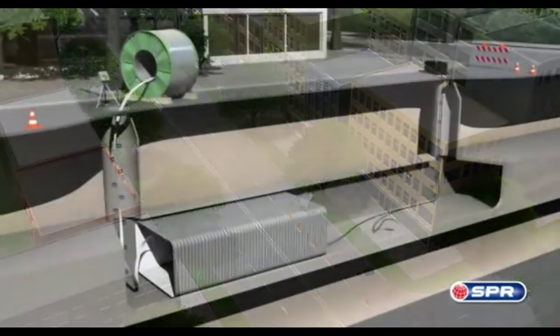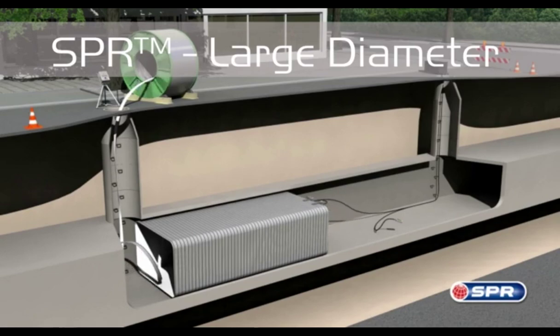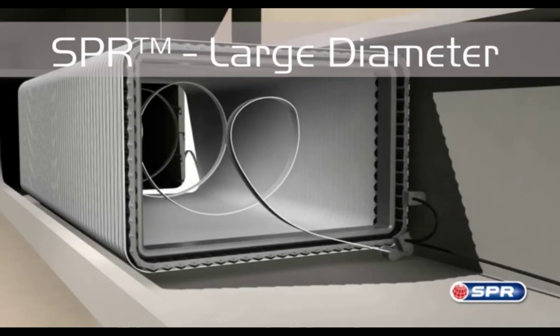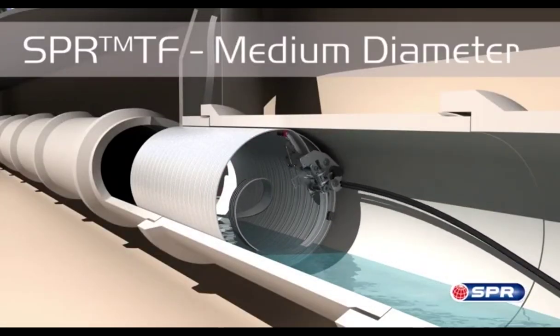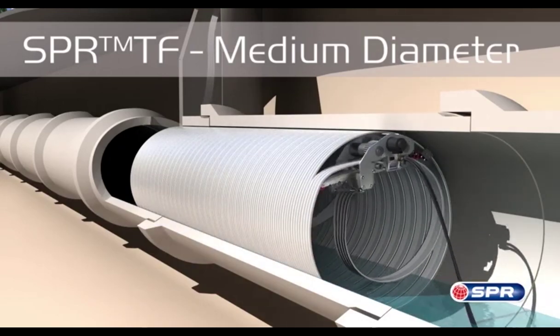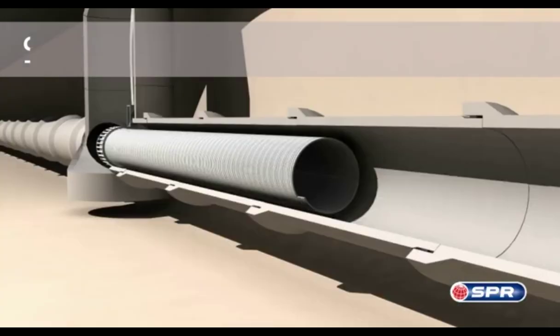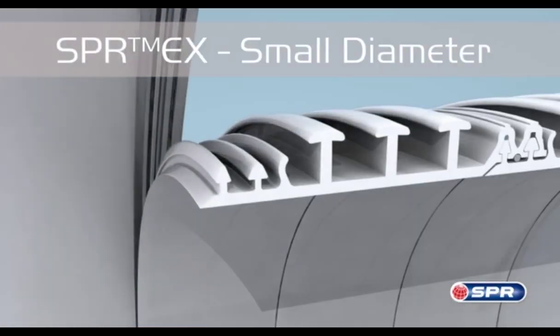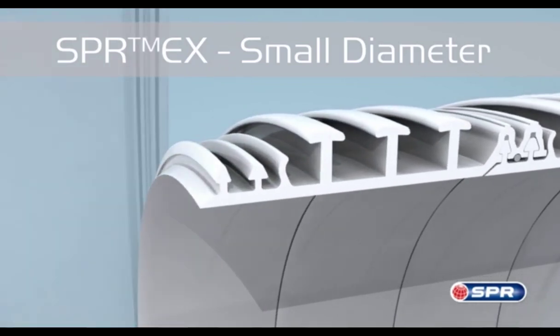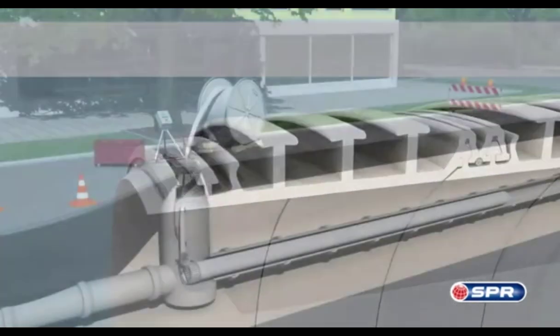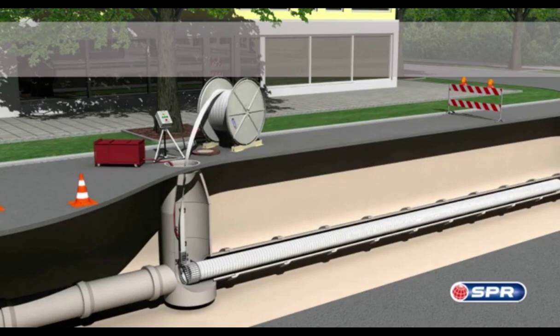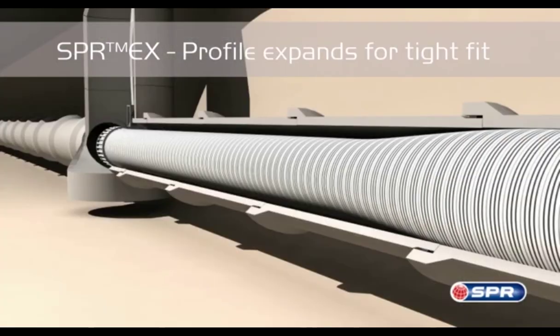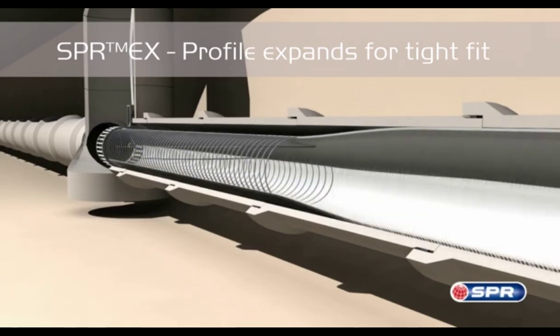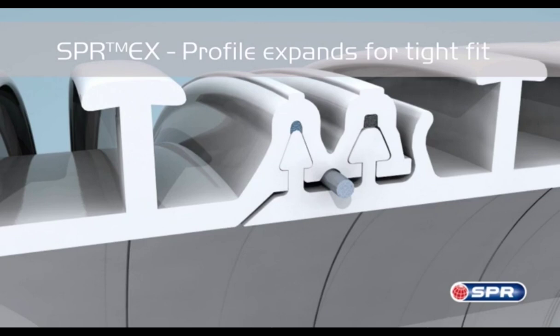There are three methods for installing spiral wound liners that vary by pipe diameter and shape. SPR™ is a solution for large diameters able to renew round and non-round shapes. SPR™F rehabilitates mid-range diameter pipelines. The PVC liner is wound directly against the pipe wall by a traversing machine, resulting in a tight fit. For small diameters between 6 and 42 inches, there's SPR™EX. PVC liner is wound by a static machine that sits at the host pipe entrance. SPR™EX is initially installed at a fixed diameter. Once the liner reaches the far end manhole, the expansion process begins. Wire within the liner is pulled, severing the sacrificial lock inside the profile. This process travels back towards the winding machine. This enables successive wraps of PVC profile to expand against each other, increasing the liner's diameter to fit tightly against the host pipe.